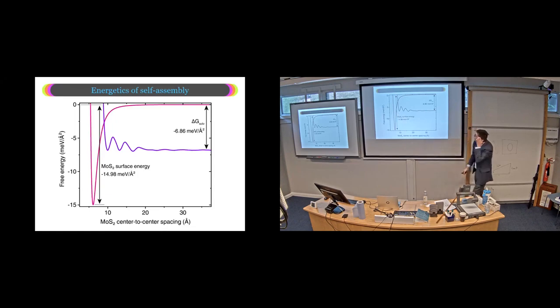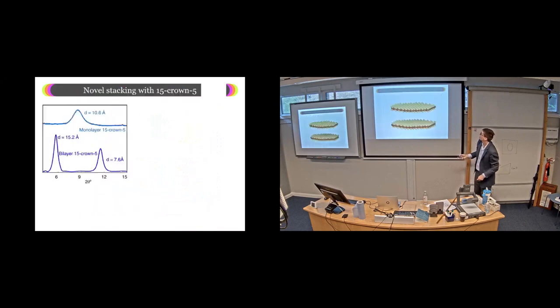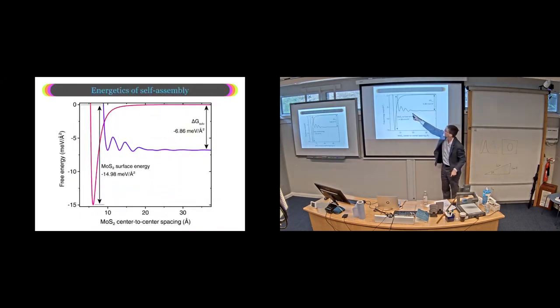These simulations allow us to actually extract a potential energy curve for the pulling together or the separation of these two MoS2 sheets. So what we see here is that as we pull them together from about 40 angstroms down to the bulk interlayer separation, that the system undergoes a series of oscillations. So this dip right here, low energy corresponds to three layers. That's two layers. One layer, as we saw in the simulation. And then this, of course, is the zero layers. And somehow, the self-assembly process stops when we get to a single layer that's left. That's interesting. And we suspected that the reason for it stopping when it gets to one layer is because of the height of this barrier. So you can actually kind of imagine why this happens. So imagine that we want to push this together and squeeze out that molecular layer. So as we compress, the potential energy goes up as we see in the plot. But at some interlayer separation, those molecules are going to get kicked out from the interlayer space. At the moment that they get kicked out, we lose all of the van der Waals interactions between the molecules and MoS2. And that makes it highly energetically costly to kick those out. So that is essentially the effect that gives rise to this very high barrier that prevents the system from going from this metastable state to what is clearly a much lower state in which the molecules have been totally kicked out. So we trapped the system here.